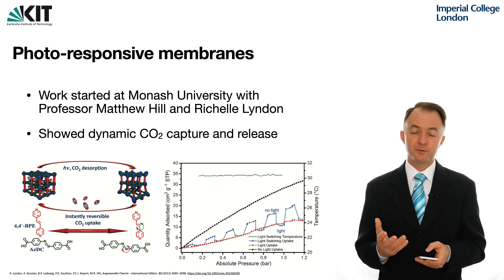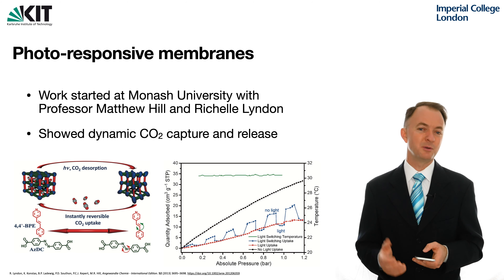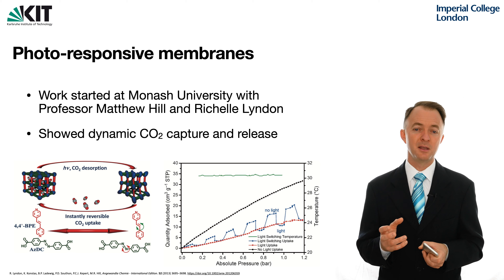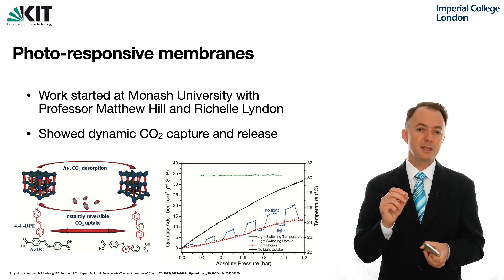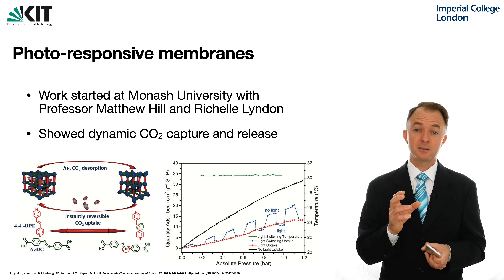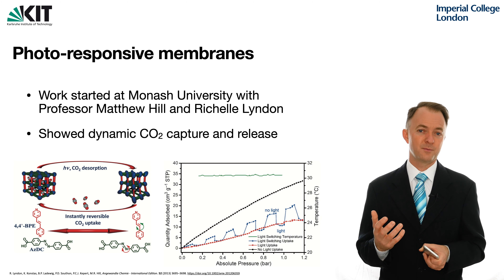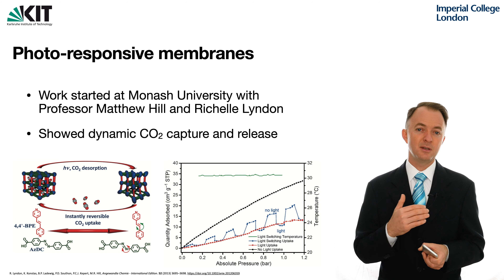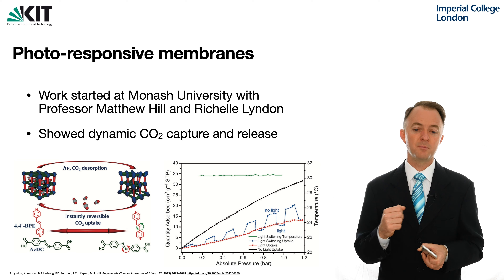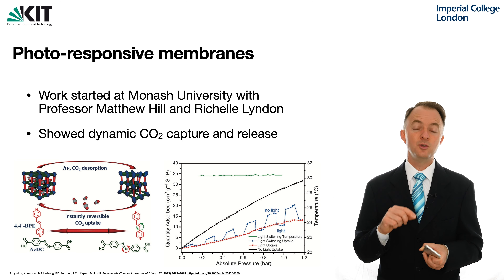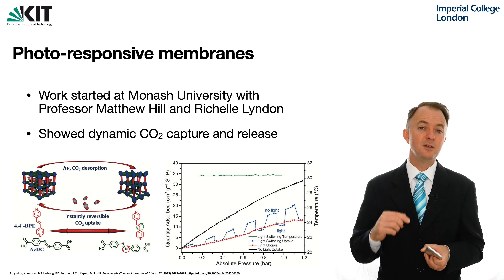This work started at Monash University with my colleague Matt Hill and our first joint PhD student Richelle Lyndon. What we showed is that you can use a photoresponsive metal-organic framework — in this case a fairly complex interpenetrated MOF — to make a dynamic photoresponsive CO2 sorbent. You synthesize this material as a powder, conduct an adsorption isotherm using CO2 as the adsorbate, and dynamically change the conditions by switching light on or off. If you constantly illuminate the material, you get a lower uptake of CO2; with no illumination, you have a higher uptake. If you dynamically switch the light on in between, you can get the extent of adsorption to move between those two points.